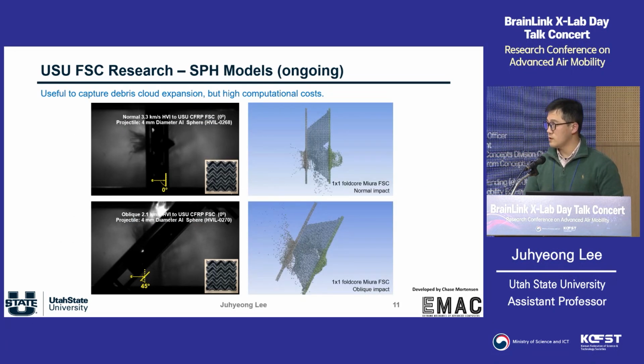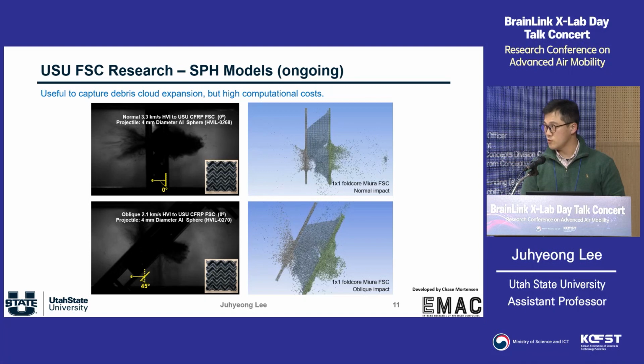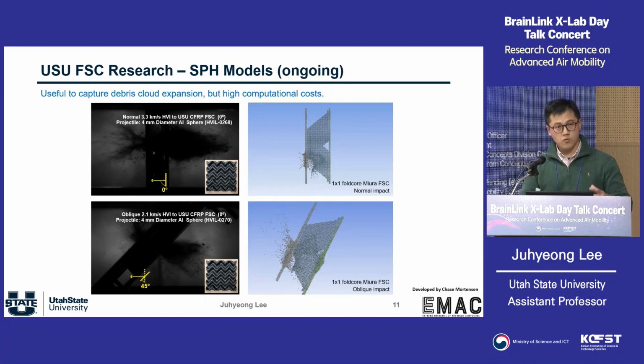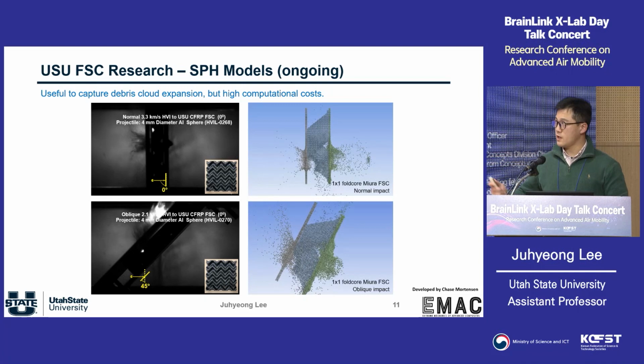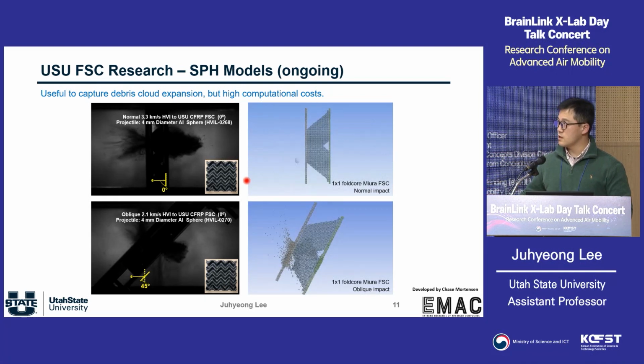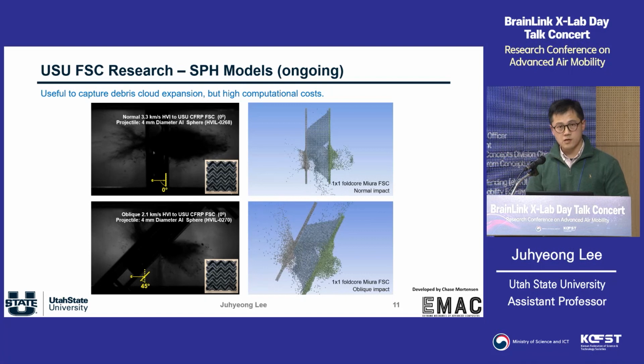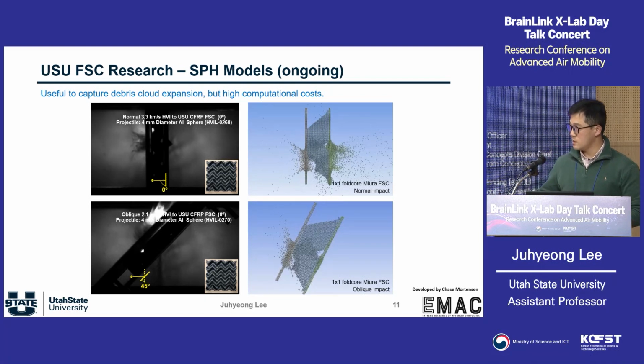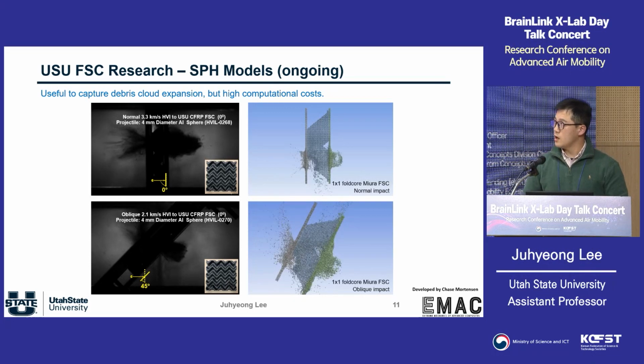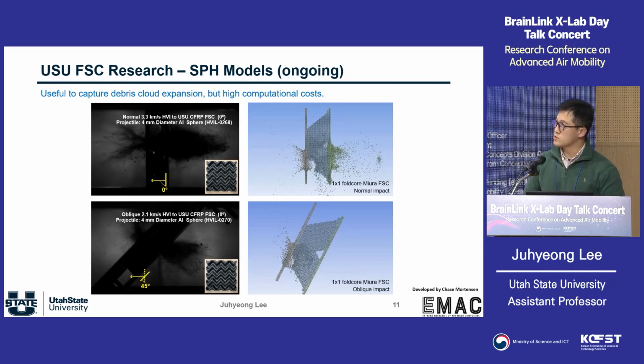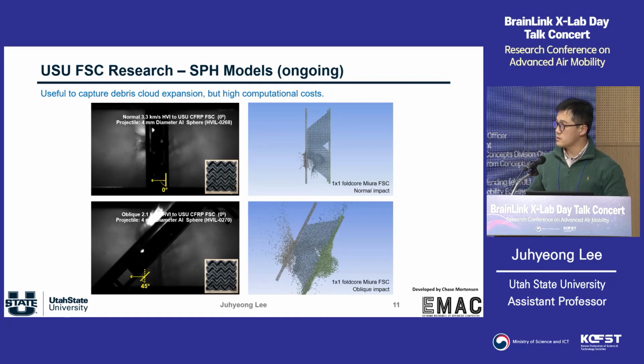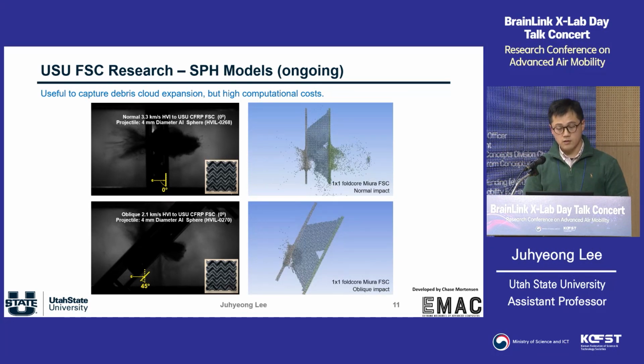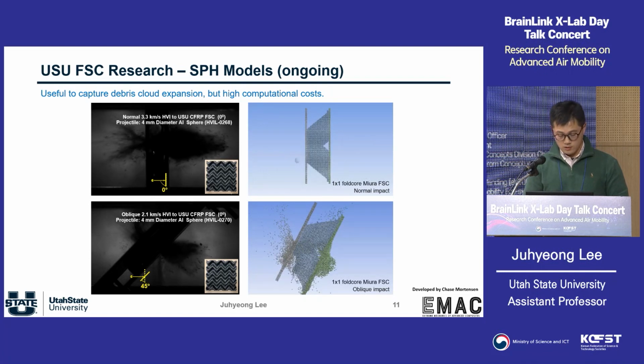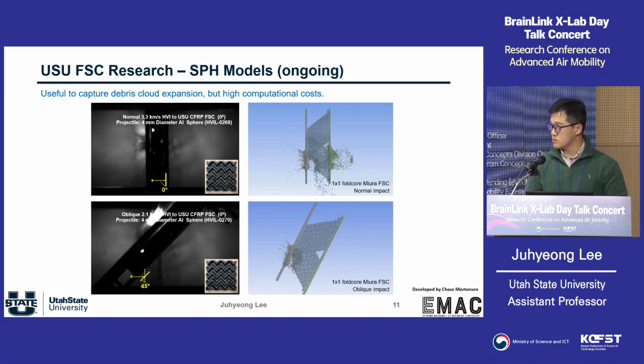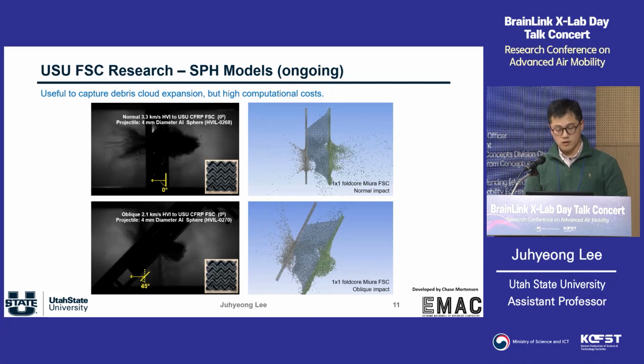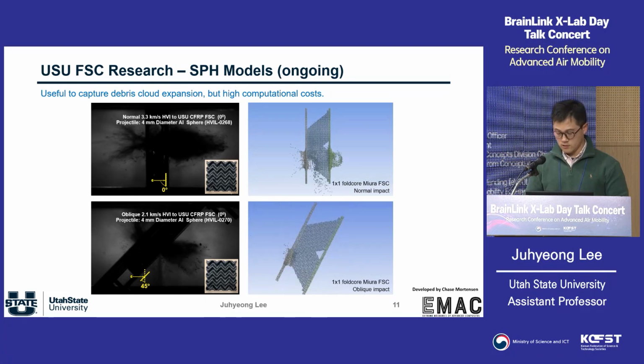And also, depending on your mission, you may want to predict the cloud formation of this debris cloud, because each individual broken piece can drive a secondary impact. That means secondary damage. So if you want to predict all this cloud behavior, we used a smooth particle hydrodynamic code, and each individual particle can be considered as a fragment. So we did some work, and then we have additional modeling and testing going on to evaluate very different performance on this new system.